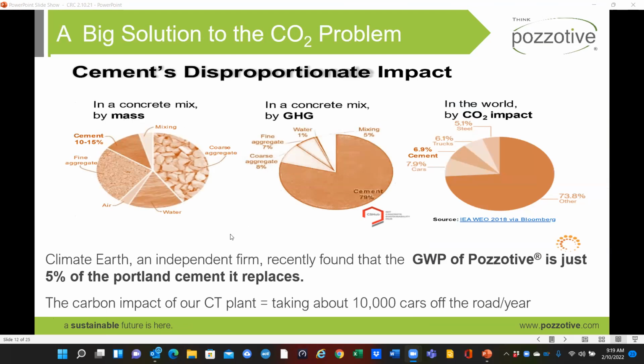This graphic just gives you a sense from a climate perspective, the impact that cement has on a concrete mix. The left pie chart shows you that cement only makes up 10 to 15% of concrete, but the middle one shows you that it accounts for about 80% of its carbon footprint. That's why replacing cement in the concrete mix is so important to get that footprint down. The right graphic just shows that cement overall globally generates about 7% of the CO2 that we generate every year.